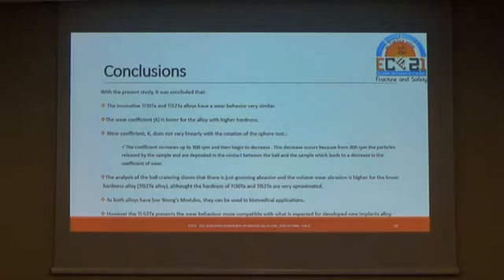For conclusions, with the present study, it was concluded that the innovative titanium 30% tantalum and titanium 52% tantalum alloys have very similar wear behavior. The wear coefficient is lower for the alloys with higher hardness. The wear coefficient does not vary linearly with the rotation of the sphere test. The coefficient increases up to 300 rotations per minute and begins to decrease. This decrease occurs because at 300 rotations per minute, particles are released by the sample and are deposited in the contact between the ball and the sample, which leads to a decrease in the wear coefficient.